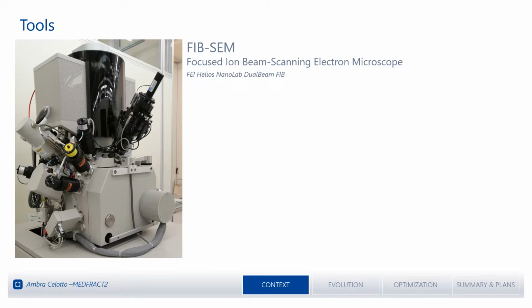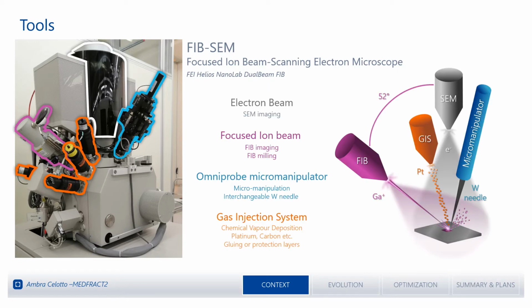The instrument used in this study is a focused ion beam scanning electron microscope, which, as you can see from the picture, is basically an SEM, a scanning electron microscope, equipped with several other tools. First of all, the electron beam allows us to image the sample. But the sample can also be viewed from another perspective, thanks to the focused ion beam, which is tilted with respect to the electron column. This is a gallium ion beam, and when focused, it allows us to sputter out material and mill the sample in order to obtain nano or micro structures.